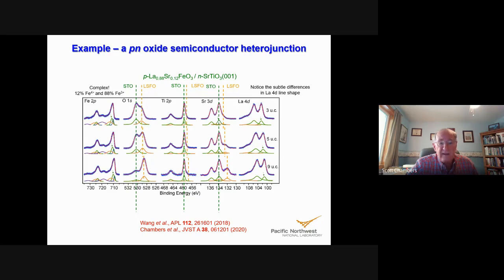But if you look over here on the other side to the lanthanum, notice that there is a different line shape for the lanthanum for the 3 different thicknesses. And you can tell that by the valley between the 2 different features in the lanthanum 4d. So what's up with that? Well, that suggests that there's a built-in potential. There's band bending, if you will, in the LSFO.